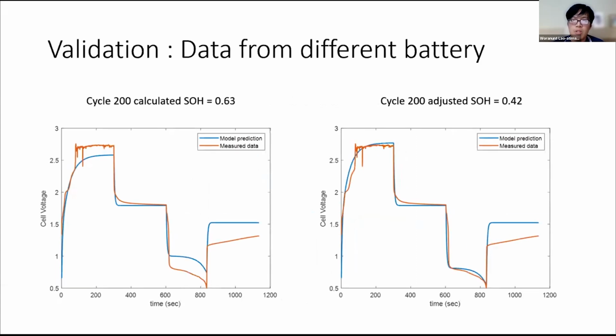Another example is from cycle 200. The result is the same as cycle 100. State of health has to be adjusted lower to get a better result. This result emphasizes that there might be some incorrectness in the definition of state of health. However, the LPV model was able to sense the changing in the battery aging via the proposed state of health. By defining state of health properly, the model might be able to predict the data more correctly.